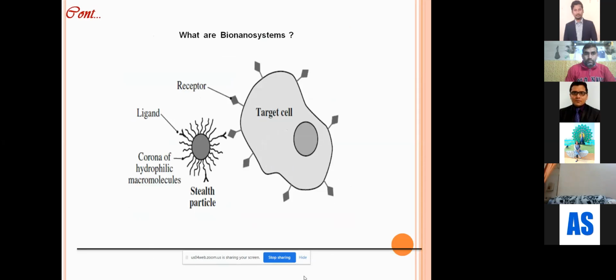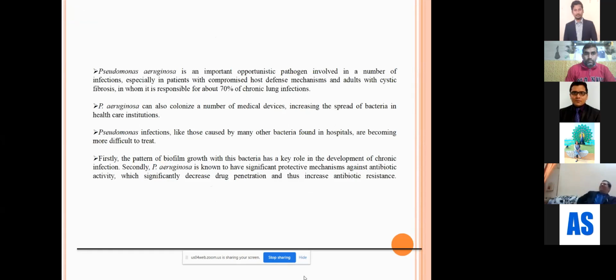Now we have come across what is nanoparticle, what is magnetic nanoparticle, and why we want to functionalize nanoparticle, and why we want to target the nanoparticle with the microbial cell. So a bio-nanosystem is the system where you want your prepared nanoparticle, either in the nanosphere range or dual core shell nanoparticle, to bind to the specific receptor site and target the cell, or you can control the biological system. So the work which we have done was able to control the growth rate of Pseudomonas aeruginosa, which